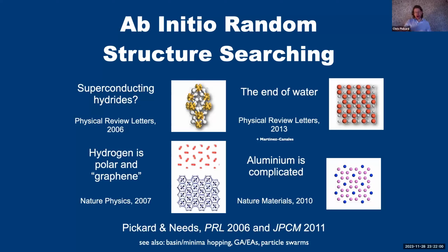Together, we were able to explore a wide range of materials behavior at these very high pressures, and often discover things that had not been anticipated before, but often confirmed by experiments not that long afterwards. So in my case, the first application of random structure searching was to studying a suggestion by Neil Ashcroft that silane, SiH4, might become superconducting at high pressures. And in fact, that's the paper where the AIRSS algorithm, or the random structure searching algorithm, is first introduced in a short paragraph that explains how you can discover crystal structures from first principles.